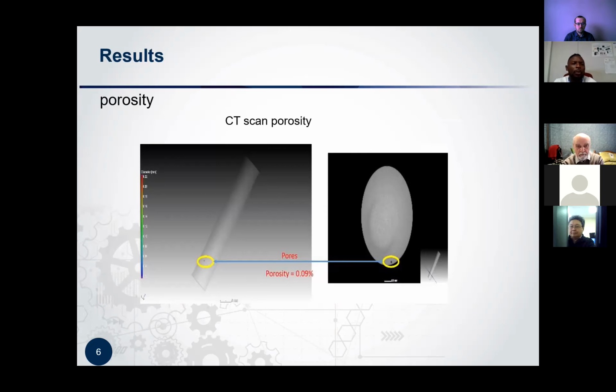And so for our results, just to show you that we were able to produce something which was dense, we took our specimen for micro CT scan, and we found that the porosity was about 0.09%. My guess is that this was just a foreign particle. As you can see, this pore is not really randomly distributed. So we were satisfied with that.